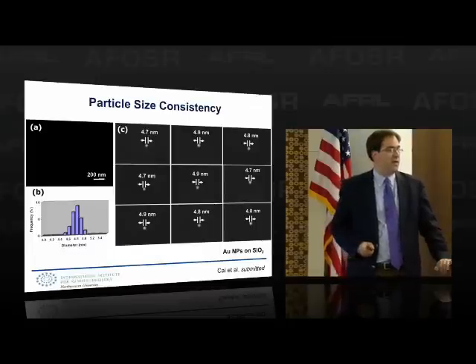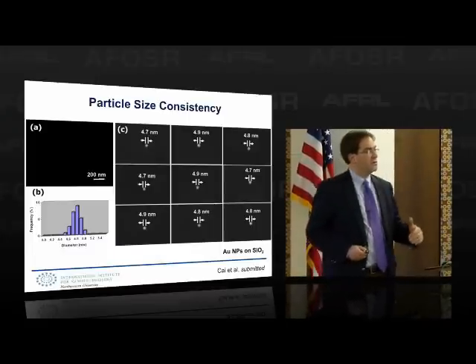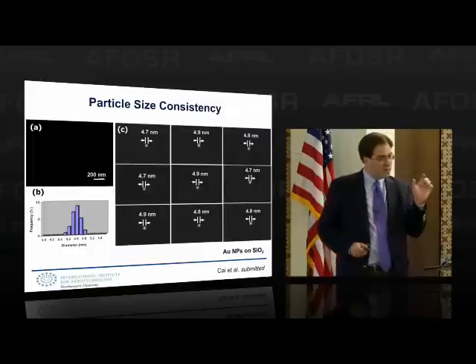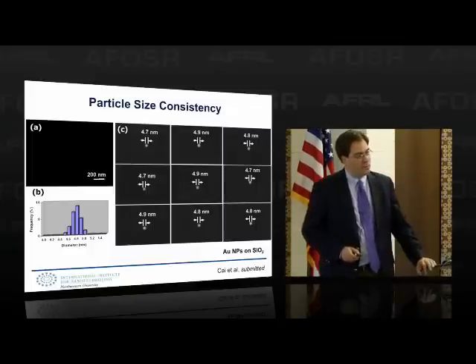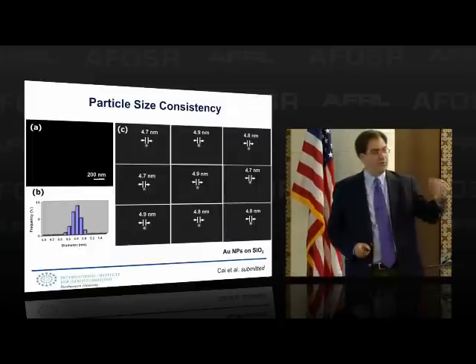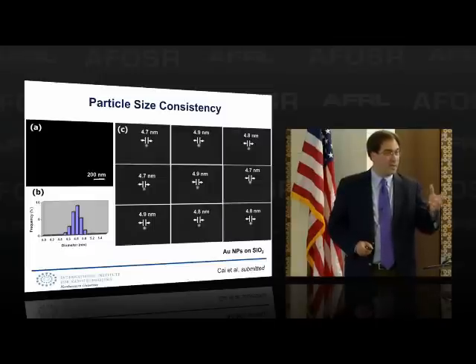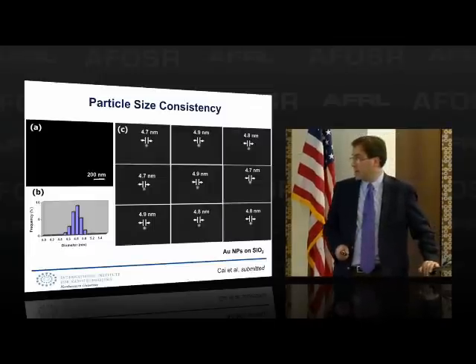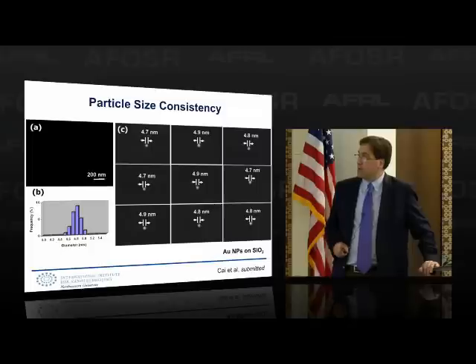I don't think you could make these even with the best known solution synthetic methods. So this is really a very fine control over particle size, because I can't use up obviously more gold atoms than I have, and the polymer feature defines how many I actually have. And here you can see it's plus or minus a tenth of a nanometer.